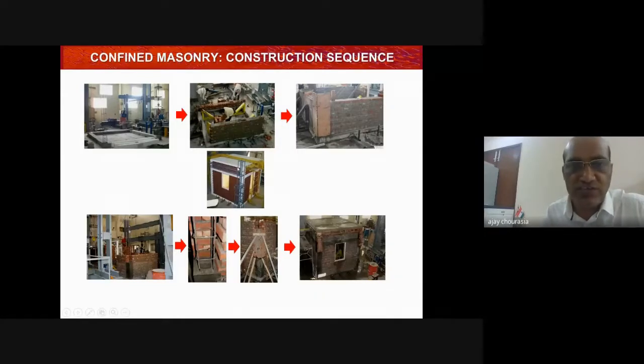So how was the construction made in the laboratory? We first laid the plinth beam, which is adequately connected to the strong floor of the test floor. Through this beam, we erected the rebars, 4 10 mm diameter bars at the corners, and the masonry work was done up to 1.2 meters, leaving a teething of 40 mm at the ends. After the construction of two perpendicular walls, the shuttering was provided in this fashion and concrete was poured. When the concrete was in a green state, teething was created by inserting a brick and then removing it. After doing so, the subsequent brickwork was carried out again.